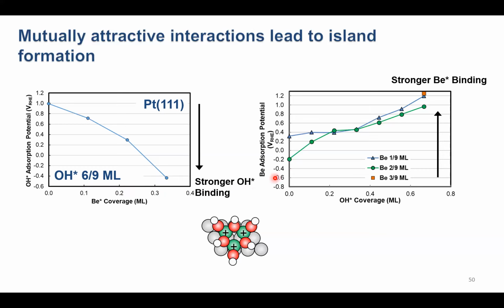And we can look at the beryllium adsorption potential as a function of OH coverage and see we also have a promotion of beryllium adsorption with increasing OH coverage. Again, what this means is that we have mutually attractive interactions between beryllium and hydroxide that lead to this island formation on the surface and this hysteresis that's observed in the voltammograms in this first order phase transition.